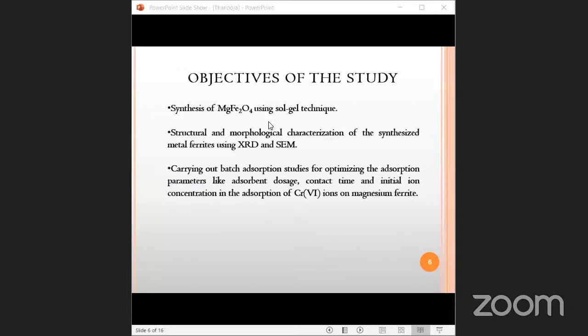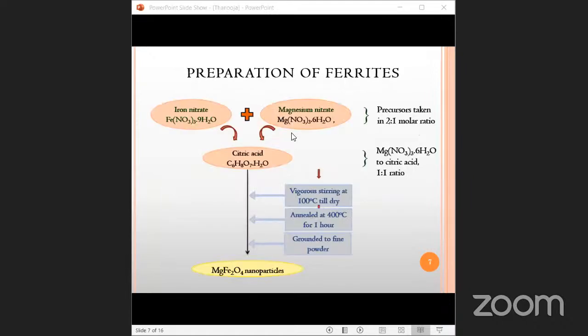The objectives of this study are the synthesis of magnesium ferrite nanoparticles using the sol-gel technique, its structural and morphological characterization using XRD and SEM, and carrying out batch adsorption studies for optimizing various adsorption parameters. Coming to the preparation of ferrites, the precursors, iron nitrate and magnesium nitrate, were taken in 2:1 molar ratio and added dropwise to citric acid, which is acting as the fuel. The solution was then dried at 100 degrees Celsius to a fluffy gel and was annealed at 400 degrees Celsius to obtain magnesium ferrite nanoparticles.